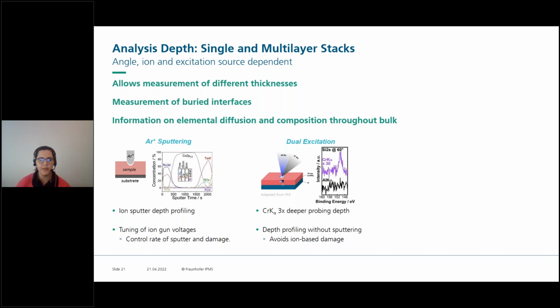For example, you have a plot here where you see, again, binding energy on your x-axis and intensity on your y-axis, and it's comparing a silicon 2s signal at an angle of 60 degrees. You can see with the aluminum Kα that you still do not reach the silicon substrate, you do not see a signal. However, with chromium Kα, you can clearly see a signal at this given setup. So this tells us that with chromium, we can indeed reach deeper probing depth.